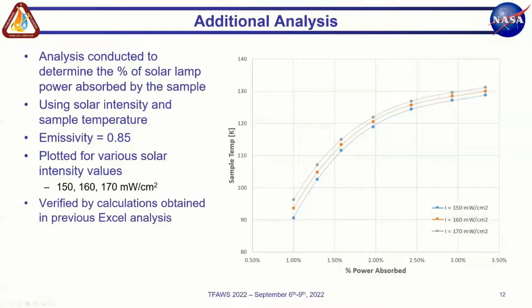All that was done, so basically just give a quick example. If we have a solar intensity input of, let's say, 150 milliwatts per square centimeter, and the sample temperature is about 90 Kelvin, the sample shows us it is absorbing about 1% of that solar flux input. And the results shown here were verified by calculations obtained in a previous Excel analysis.